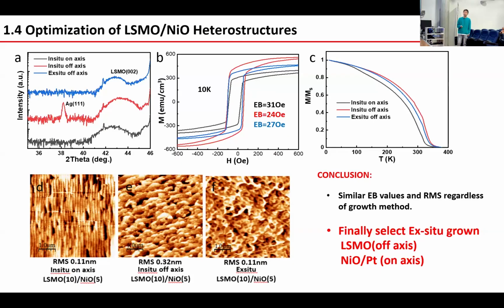Quality is quite similar, and also the M-T curve shows the off-axis relatively higher than the on-axis growth. This mimics the previously discussed LSMO growth, where the off-axis has a higher magnetic property than the on-axis. And also the roughness is quite similar from the AFM image. So in order to better investigate the LSMO magnetic property, we are choosing the mixed growth, with LSMO off-axis and then growing nickel oxide and platinum on-axis.